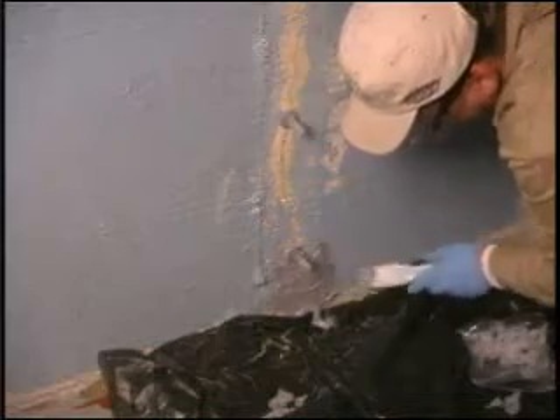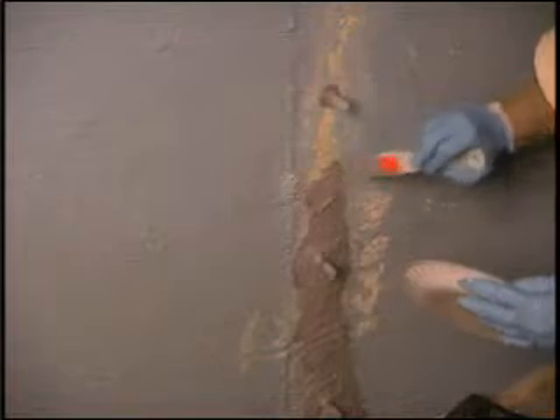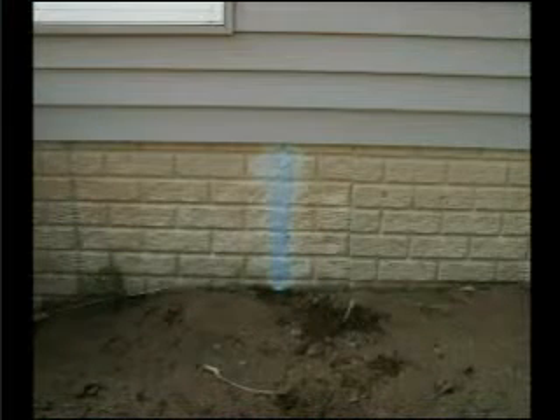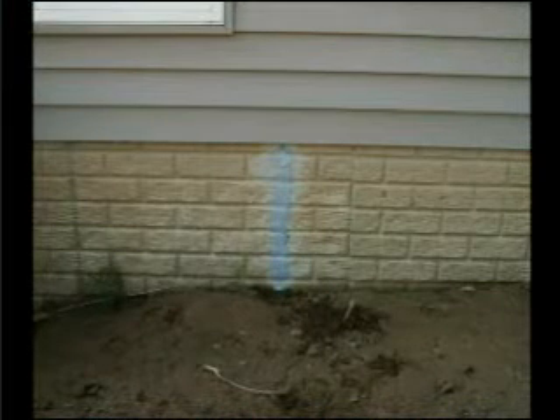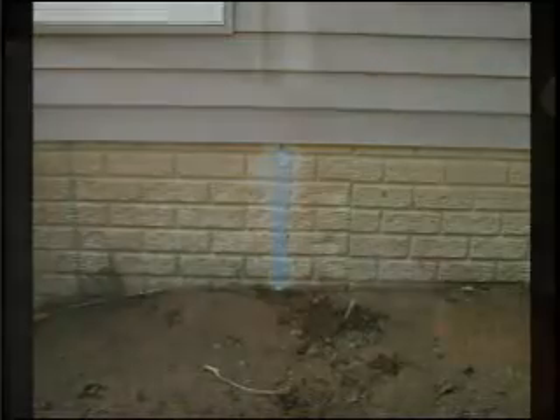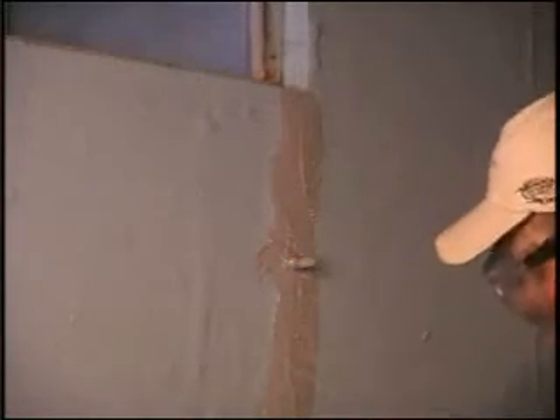The next step is to work the mixed surface seal epoxy paste along the entire length of the crack using the plastic trowel. If the crack goes to the top of the wall, you will need to apply a layer of sealer above the soil grade on the outside of the foundation, as shown here. The recommended epoxy application is 1/8 inch thick and 2 inches wide.